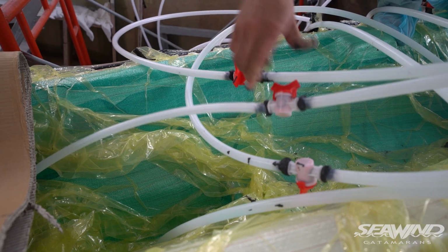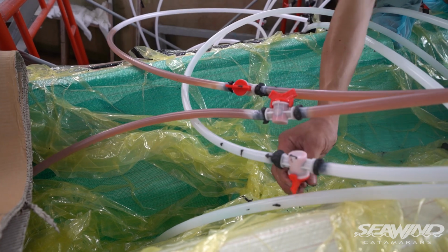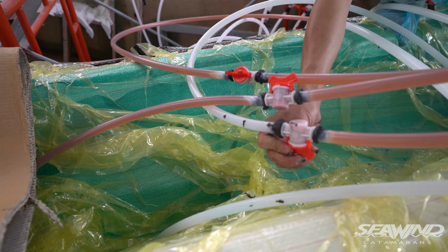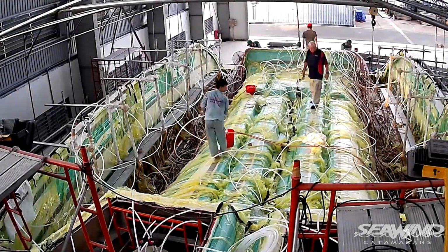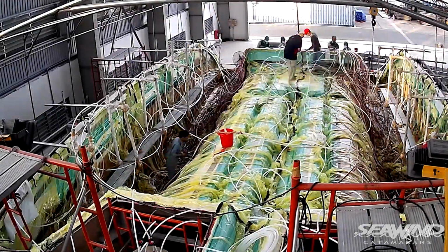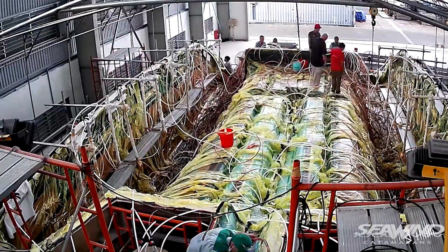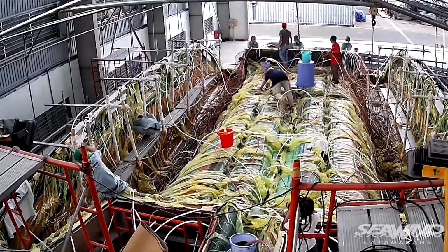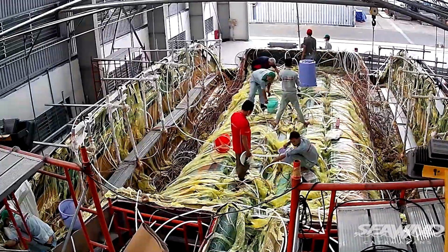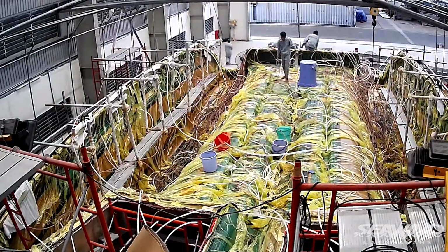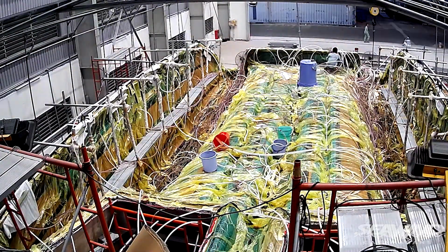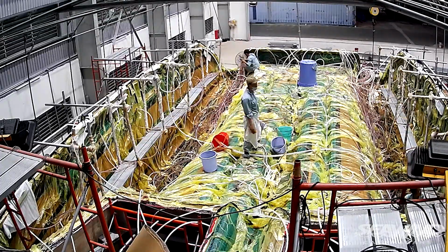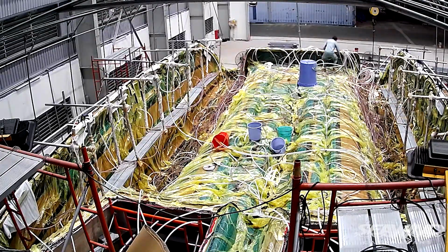Following our infusion strategy, we open the valves one at a time, and the vacuum draws the resin into our fibres and core. The resin will travel along the path of least resistance and flows along the mesh. The grooves and perforations in the foam then channel the resin in the right direction towards our perimeter vacuums. As each area fills with resin, we'll close the valve and open the next one until the entire boat has been fully impregnated with resin. This process takes about 1 hour to complete and will then remain under vacuum overnight.